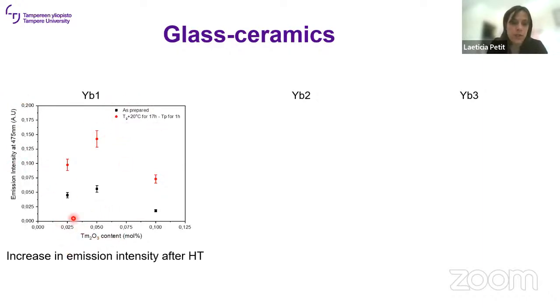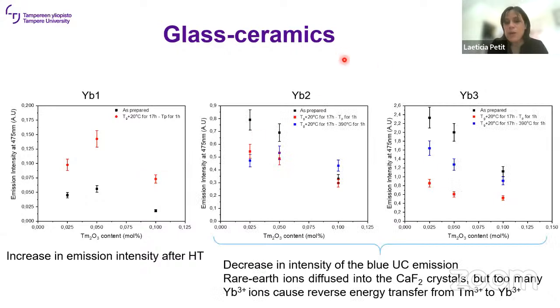So we measured the intensity of the blue emission as a function of the thulium concentration, before and after heat treatment. When we have low concentration of ytterbium, we have an increase of the intensity after heat treatment for all the glasses. And this is due to the presence of the rare earth ions in the calcium fluoride crystal. However, in the YB2, so the glasses prepared with 2 and 3 mol% of ytterbium oxide, we have a decrease in intensity of the blue emission.